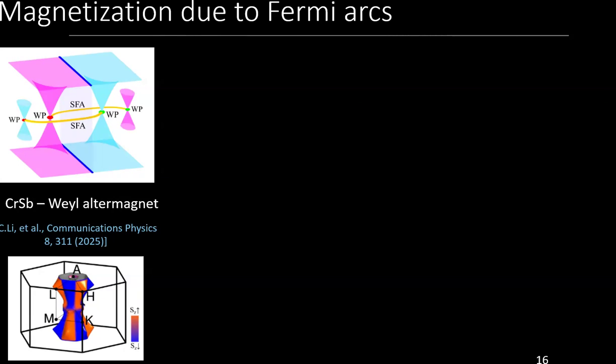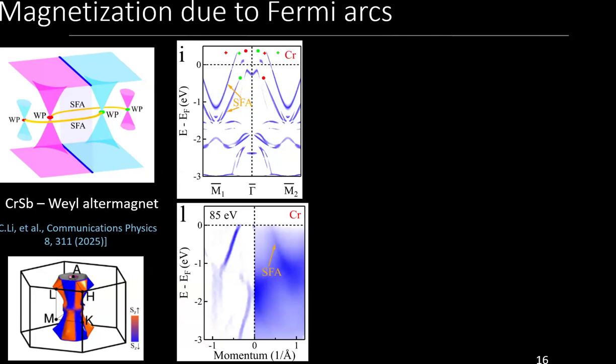And since you have a topological material, you always have some boundary. Crystals are finite. This topological material, when it ends, topology disappears. There is no topology in vacuum, there is topology in the material. So where topology goes, it should be somehow shunted at the boundary. And if we shunt the topology, we create a specific boundary state called a Fermi arc. It was obtained experimentally.